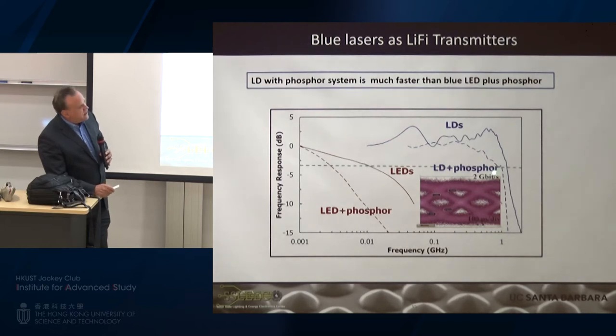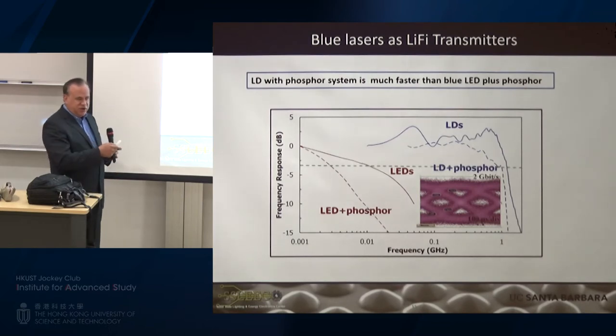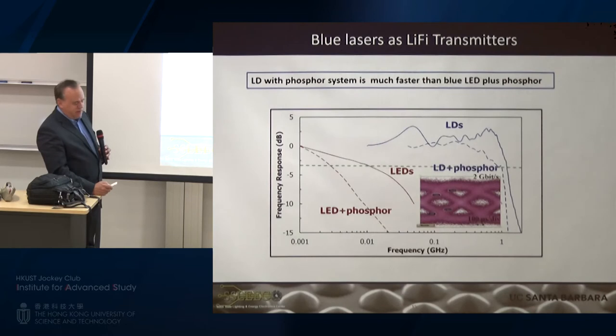And so that's the advantage. Even with the phosphor on it, we didn't slow down that much. Smaller is better. Yeah, and it's because we're small too. The problem is when you go small with micro-LEDs, then you don't get the signal. But like I showed you, we were small and we were doing 3 watts. So we gained in 2 areas.